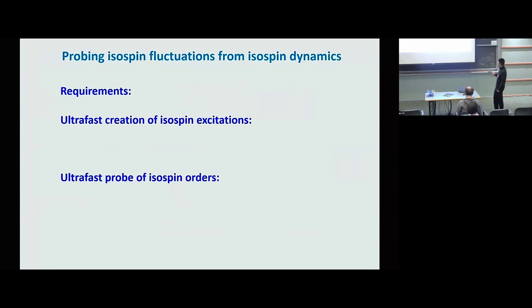And experimentally, how do we do it? Well, to achieve it, there are two requirements. First, we have to be able to create the excitations at ultra-fast time scale. And of course, second, we have to probe them at an ultra-fast time scale. So the first requirement is relatively straightforward, and is standard for optical pump probe measurement. If you want to create some excitations at ultra-fast time scale, just use the ultra-fast light or femtosecond pulse to excite the system and create some excitations. So that is fine. But the second requirement is not that trivial.